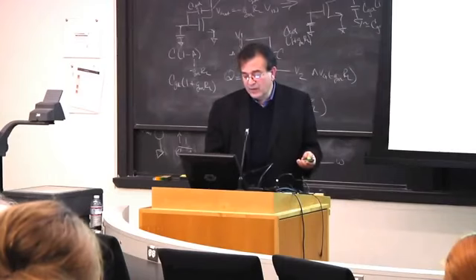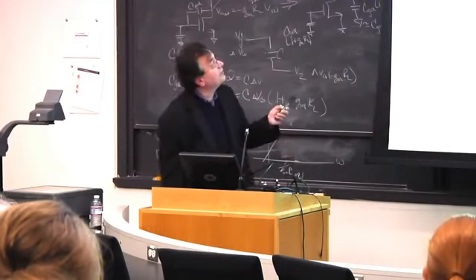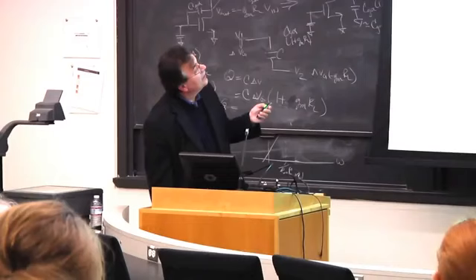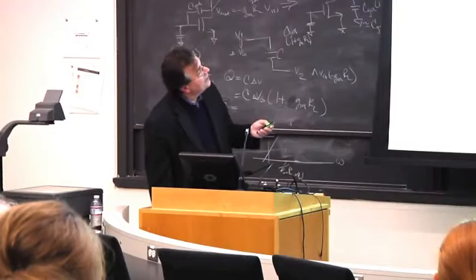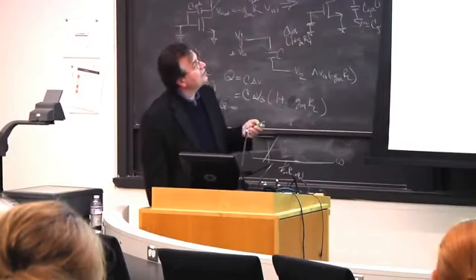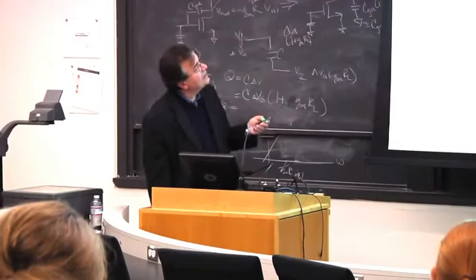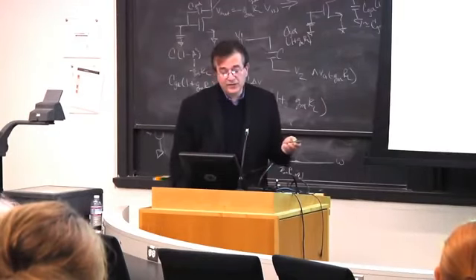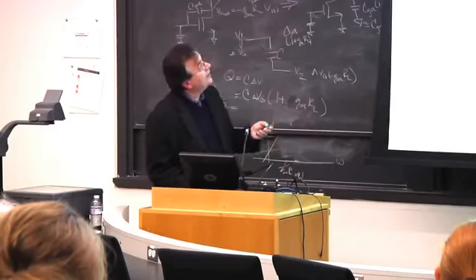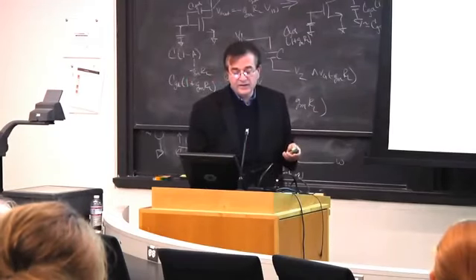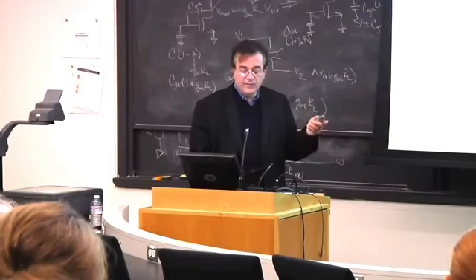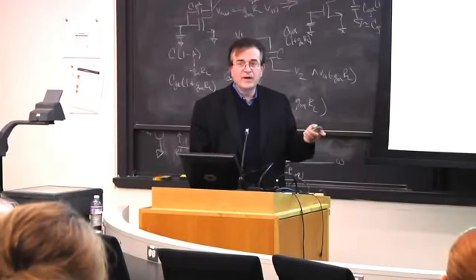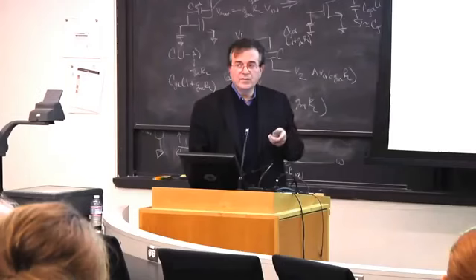Here I show the top thermoelectric materials today. It's a little bit out of date because some of the materials I showed you are not even here. But the top now, we are very close to 1.7. This is the N-type systems. This is the P-type systems. We're about 1.7 or so, 1.8. And this is good enough for some of the applications that I showed you earlier. That's why I call this a paradigm shift, because we switched from looking at single-phase compounds into looking at inhomogeneous mixtures at the nanoscale.